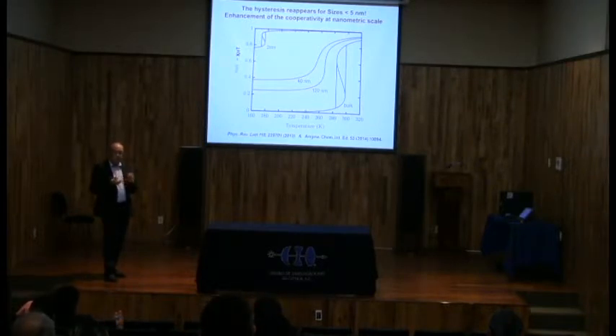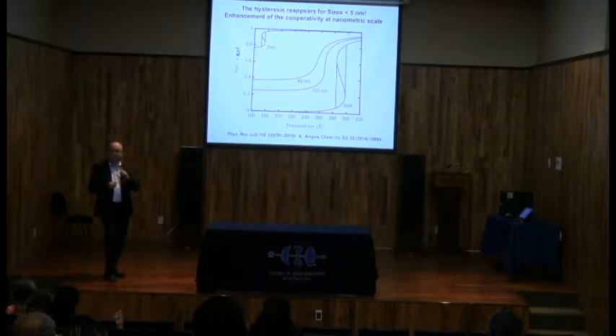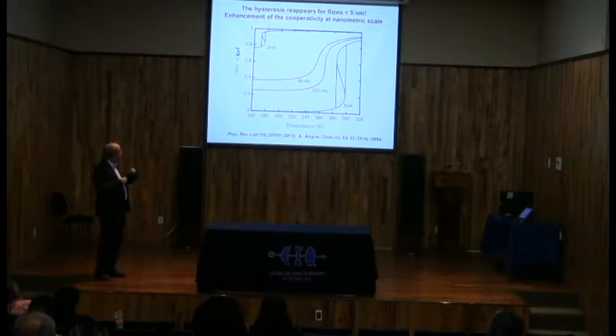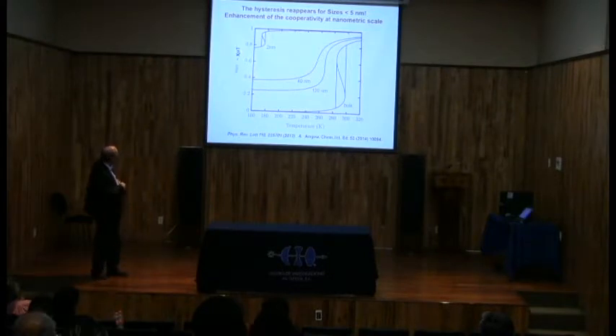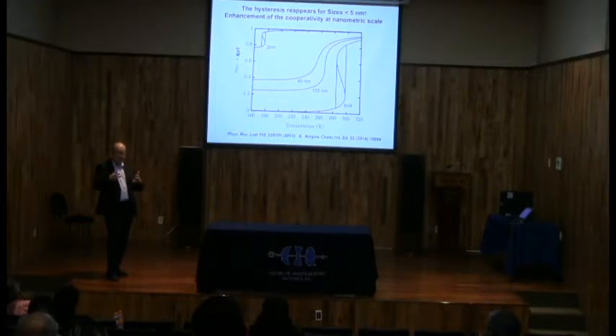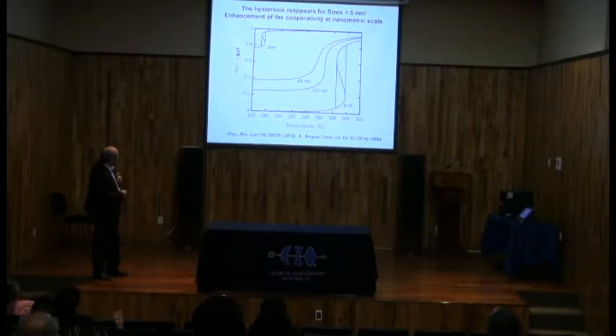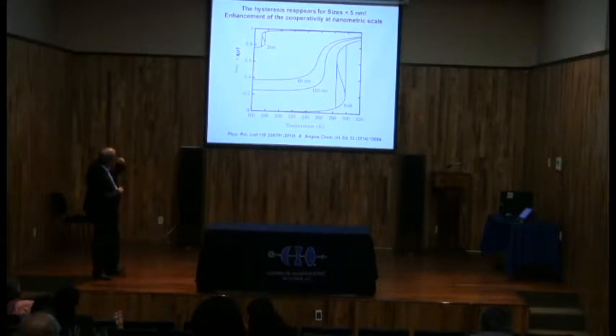So then, from this region to this one, in 2 nanometer sizes, you know you have no bulk. Okay, that means that we have some surface effects, and then we look by Mössbauer spectroscopy at the Debye temperature, for example, which measures the elasticity and the rigidity of the system because of the surface effects. So the rigidity of the system increases at very low temperature. And because the elasticity through the surface effect increases, that means that the cooperative interactions in the system increase again. So that means that when you go from bulk to nanometric systems, you cut the interactions, okay, and then you lose the hysteresis. When you still reduce your system, because of the surface effect, because of the elasticity which diverges at very low dimensions, your hysteresis appears again.